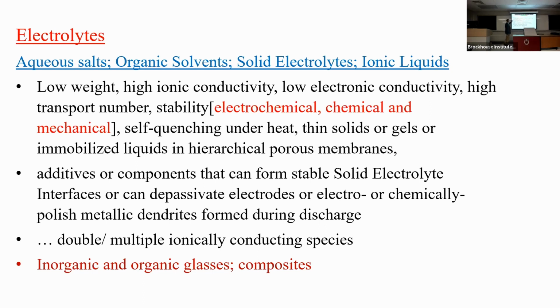So I think what we require here, these must be of low weight and high ionic conductivity and low electronic conductivity, and extremely high transport number and very stable. And also the safety features must be self-quenching under heat or shut the battery if it gets hot. Thin solids or gels or immobilized liquids in hierarchical porous membranes, so that there is good conductivity and all the properties are met. And of course, we need the right type of additives so that there is a stable interface that is formed at the anode and the cathode.